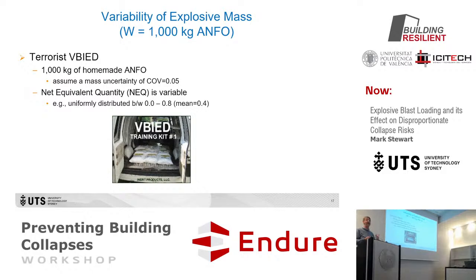A bigger uncertainty is how you mix it. ANFO has to be mixed really carefully to get the full energetic property. If it's mixed perfectly, it's going to be equivalent to about 0.8 compared to TNT, so 80% of the effect of TNT. TNT is always seen as a reference here. But if it's made poorly, it can have 0 TNT equivalence. It's just a dud, a fizzer. One example was the so-called Times Square bomb.